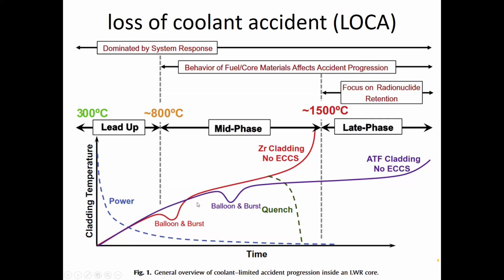So the cladding temperature will drop a little bit as it kind of expels and expands out into the surrounding area, the surrounding coolant. And as things continue, it ends up hitting around 1500 degrees Celsius, in which you have runaway corrosion occurring. At this point, it's completely exothermic, so the whole thing acts kind of like thermite to some degree, and you're producing hydrogen at the same time.